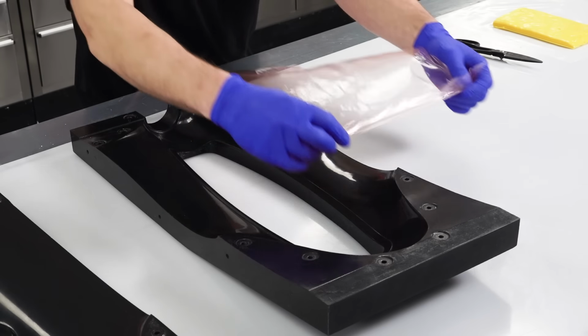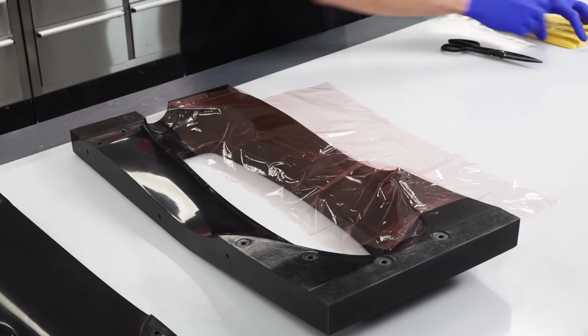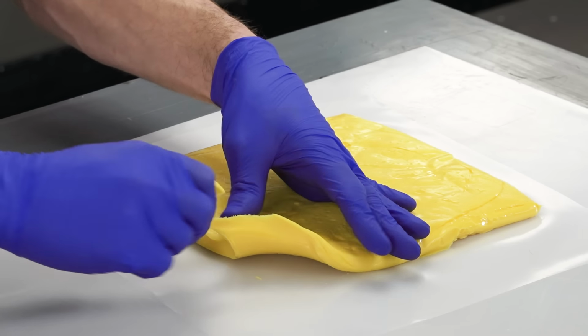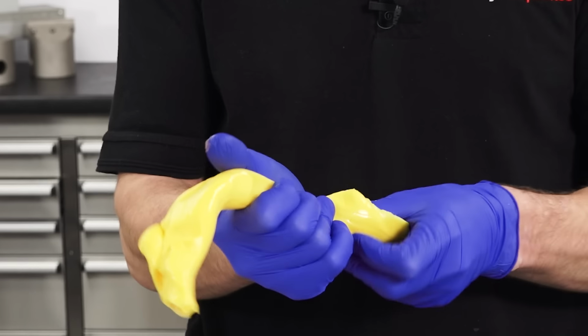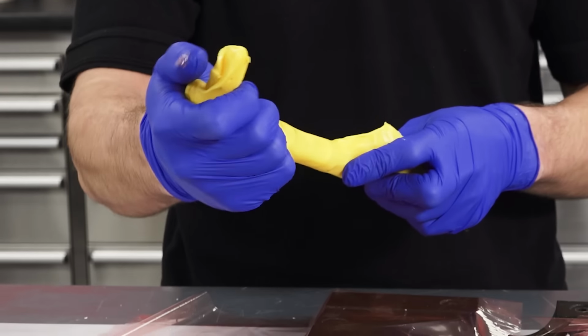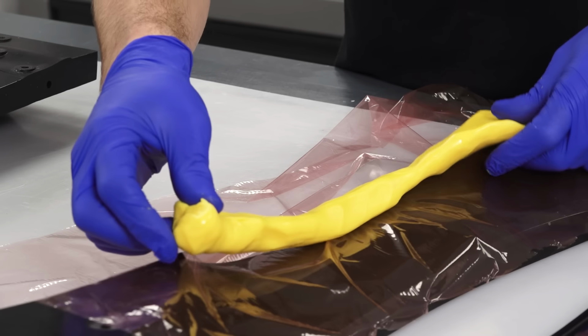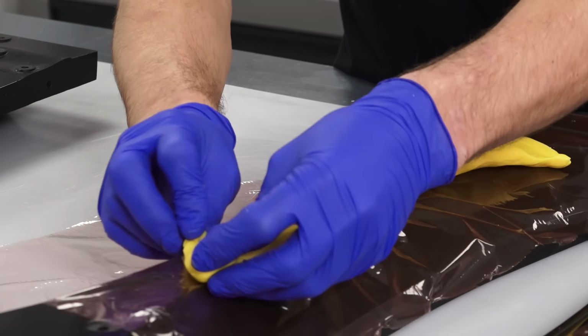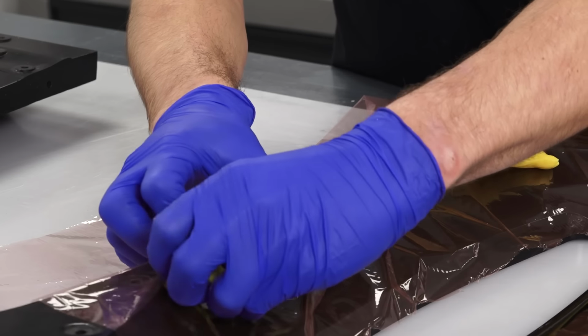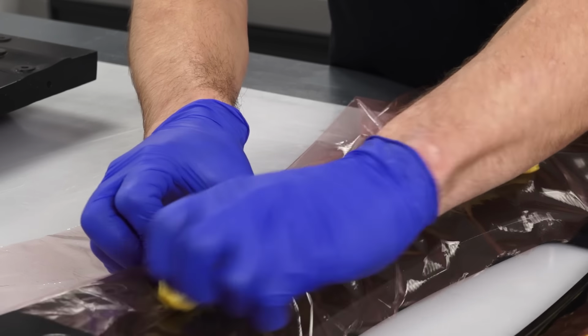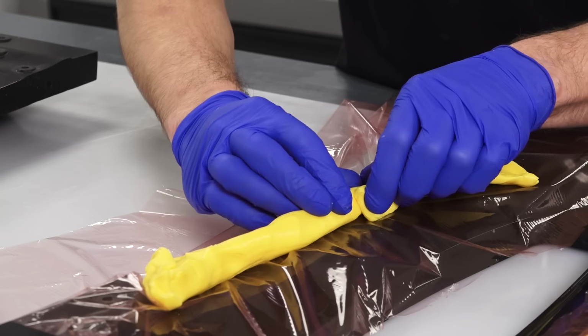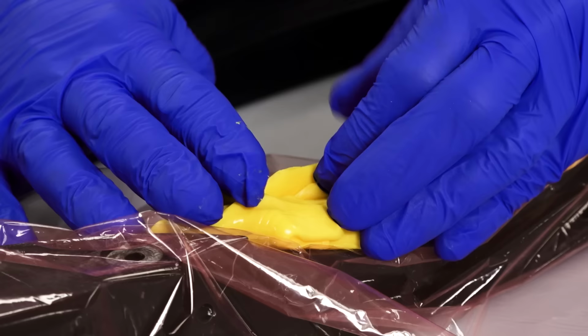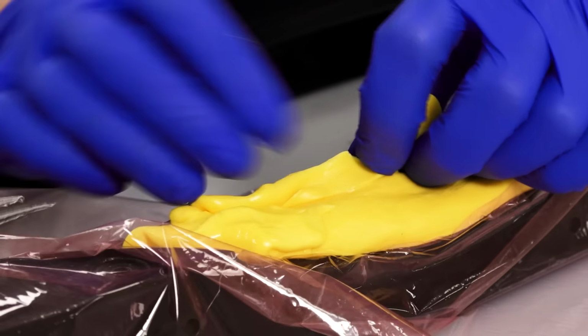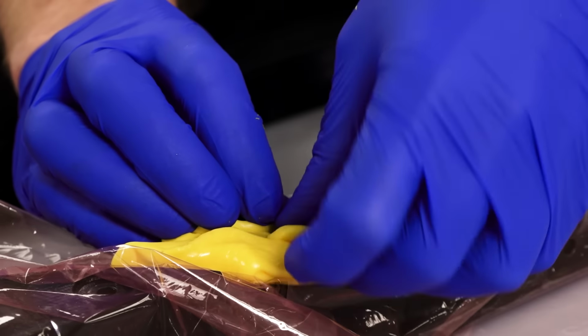So to get started, I'm now going to lay down some release film and press the material into the rough shape. When doing this, try to ensure that you don't leave voids in the silicone. You want to load in an amount that's going to be sufficient to fill in all of the details where you think that bridging of the vacuum bag could occur. It's not an exact science, but being so pliable, it's really easy to add and remove material as required.